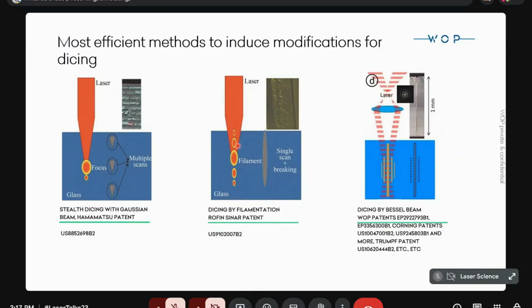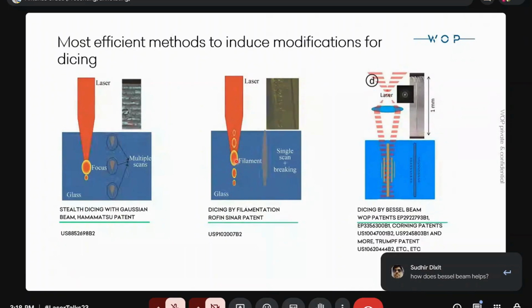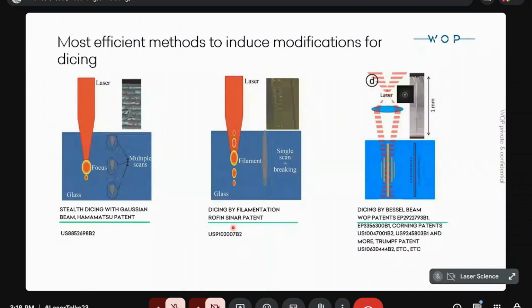If you use the effect which is called filamentation, it is patented by Rofin-Sinar. What is filamentation? It is a combination of plasma defocusing of the beam, which is focused inside, and the Kerr effect focusing it again. Here you should have many passes to get several damage lines. In a filament, it is made automatically. So it is focused, defocused, focused again, defocused again, focused again, and you have a filament, a chain of modifications along the focus line. So it is quite precise, and again you can break after one single scan.